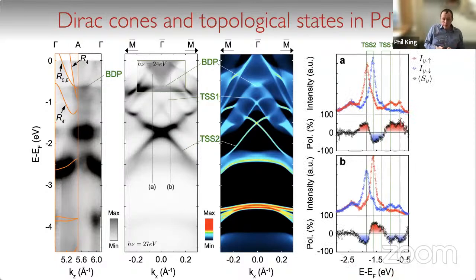And to finally confirm the topological nature of the two surface states that we see here, we can perform spin-resolved photoemission. As we move along these line cuts shown here as A and B, you have a very clear spin texture derived from this topological surface state TSS2, with a similar spin texture that derives from this topological surface state TSS1, which is our surface resonance here.